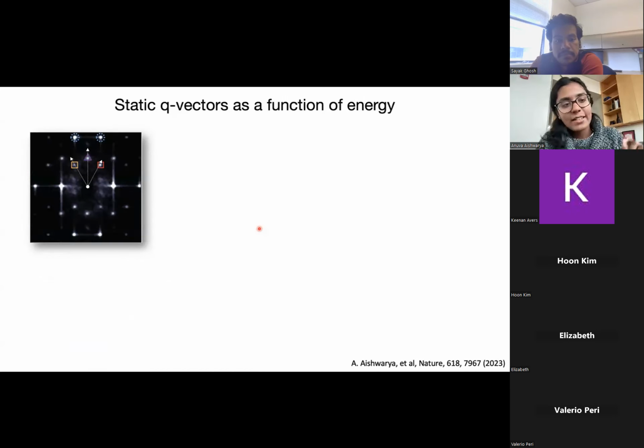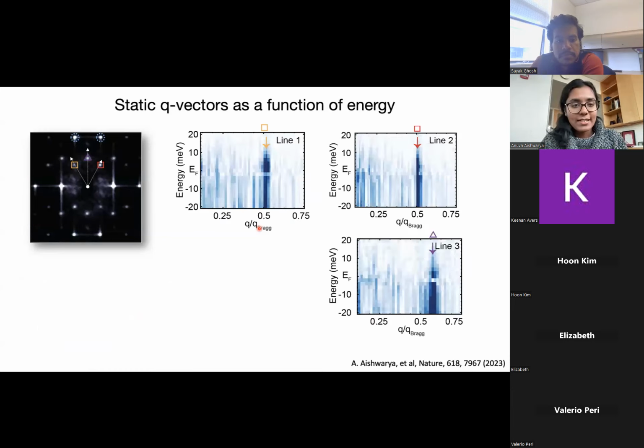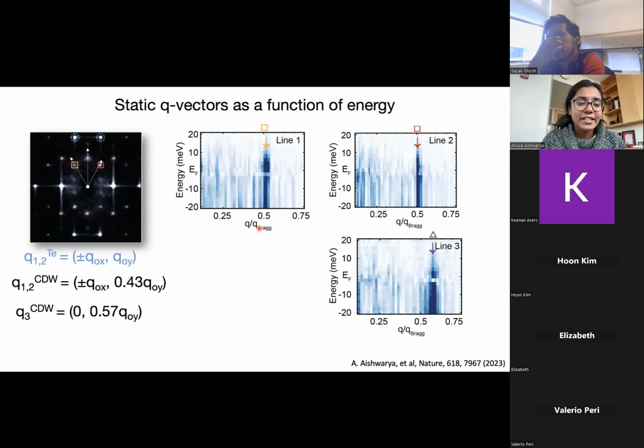So we can track the position of these Q vectors as a function of energy. And what we see is that there's no dispersion, they're static. So this is a direct indication that it is coming from static charge density wave oscillations and nothing like dispersion from quasi-particle interference, which is also known to be done through STM studies. We can measure the magnitudes of these Q vectors, and we see that all three of them are incommensurate. And the reason it appeared like almost every atom is because they're pretty close to 0.5, which is half the